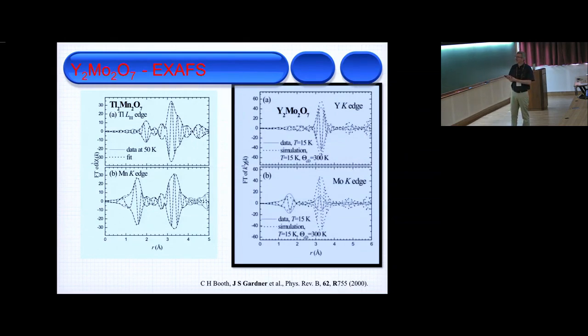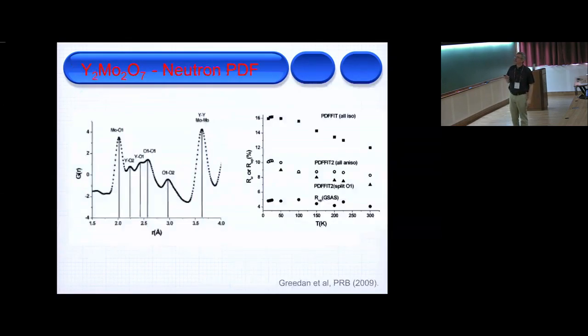But my colleagues then can parameterize this and give us some numbers that they reckon there's a 20% difference in bond length of the molybdenum sites. But on average, when you do diffraction, it averages out to 0. If you do neutron PDF, you do the Fourier transform and you get these peaks. And each peak you can relate to a different bond. One of the take-home messages from this paper by Greedon was that as they cooled down this yttrium molybdenum oxide, the fitting got worse. So it was something that got worse as you cooled down.